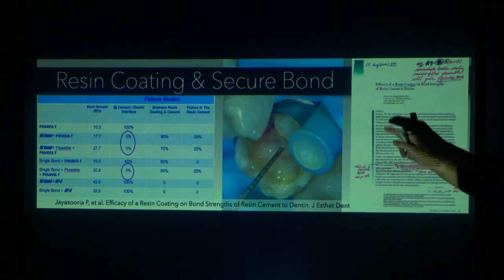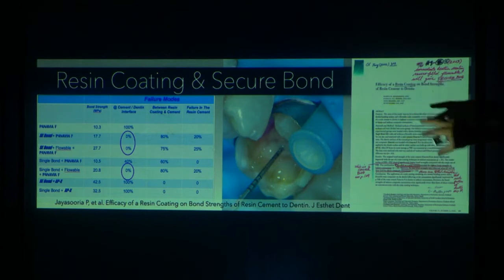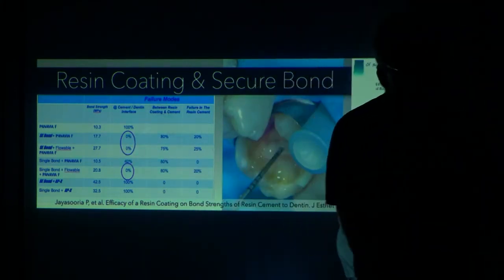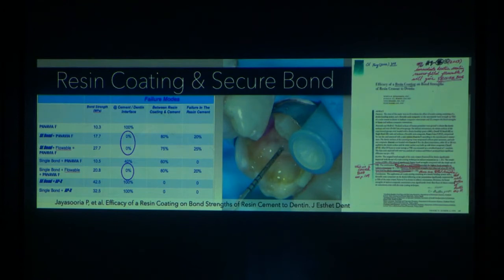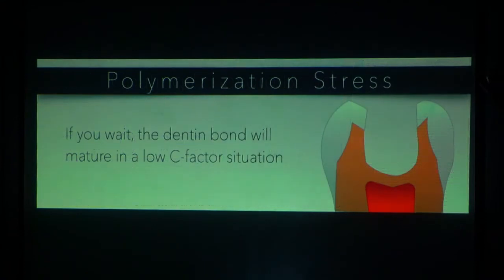But Primali Jayasuriya was at TMDU, and they made this paper on resin coating, and they found out that if you put this half millimeter and then you pulled apart the restoration, you couldn't pull it off the dentin. If you did not resin coat, then you could pull your restoration, whether it was direct or indirect, off of the dentin. So we call that a secure bond strategy, because even if a restoration fails, it's a clinical failure, it's not a biologic failure. So this was important information that came in 2003 out of TMDU, Tokyo Medical and Dental University.